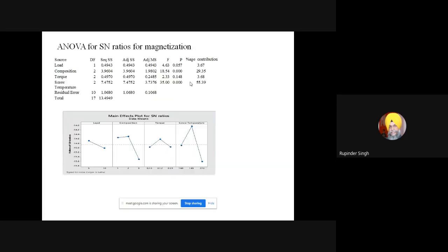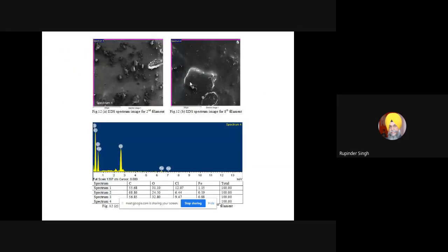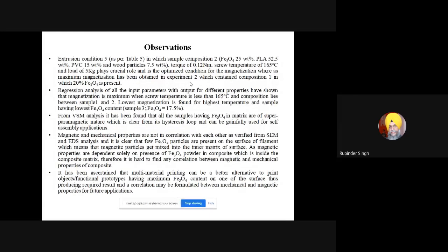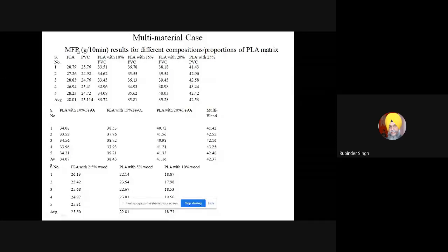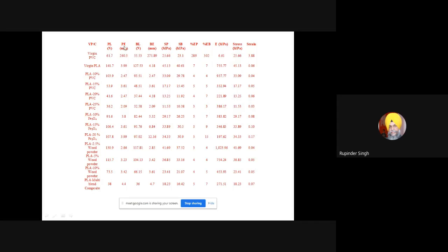Okay. Based on this, we did some parametric optimization, then some EDS based analysis for this type of material, and we are trying to have a single blend and multi blend material. Like in this particular example, you can see for a selected grade of PLA, with a number of repetitive observations, I was able to get the MFI in the range of 28. For PVC, it was 25. So we tried to reinforce different quantities of PVC in PLA, and a particular reinforcement level was selected. Similarly for Fe3O4 reinforcement in PLA, in a single blend and in a multi blend, different numbers of experiments were tried, and we tried to ascertain their peak load, peak elongation, break load, break elongation, peak strength, break strength, Young's modulus, modulus of toughness, these types of things for the different compositions.